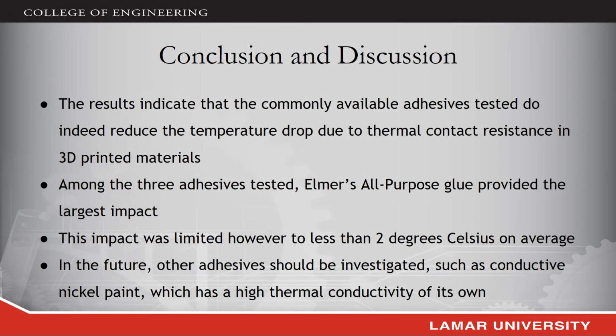In conclusion, the results indicate that commonly available adhesives tested do indeed reduce the temperature drop due to thermal contact resistance in 3D printed materials. Among the 3 adhesives tested, Elmer's all-purpose glue provided the largest impact. This impact was limited, however, to less than 2 degrees Celsius on average.